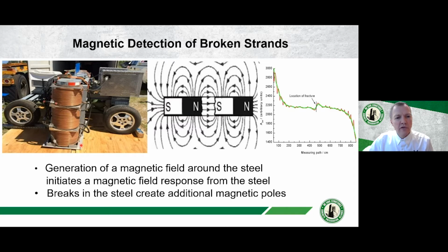When you run this over top of the concrete surface and you go over a post-tensioning tendon that is going in the same direction as the magnetic field, then you will induce a magnetic field response onto the steel itself. And when you do that, you're going to magnetize the steel, and one end of the steel is going to be magnetized south, like the magnet shown here in the center, and one side of the steel is going to be magnetized north, as indicated here.